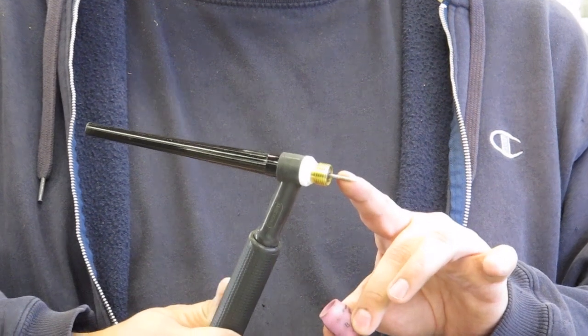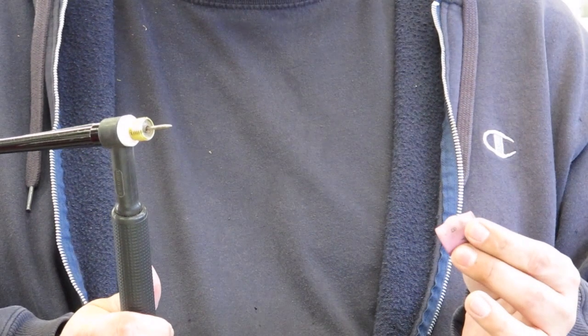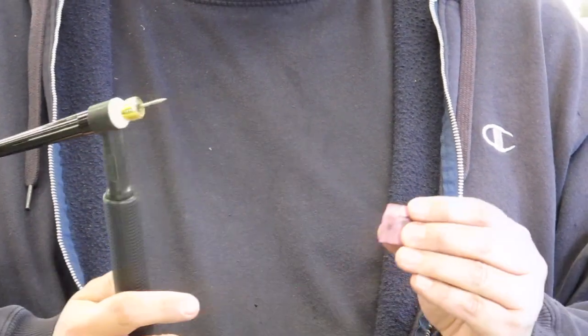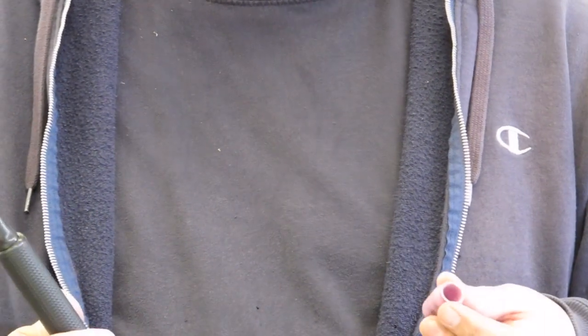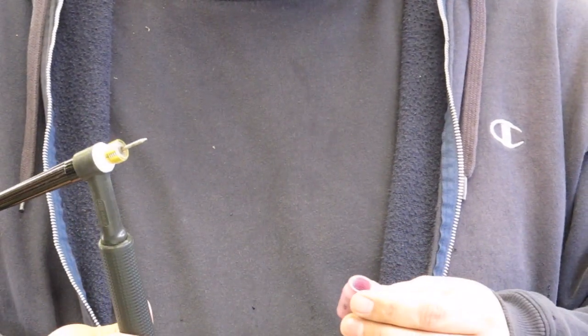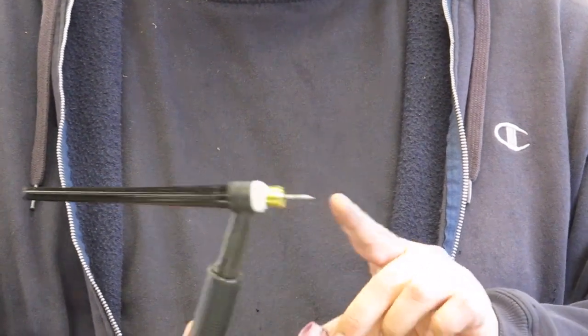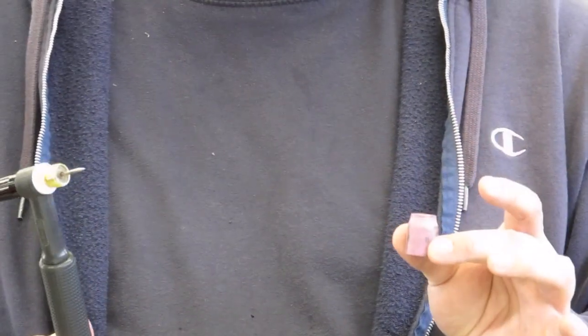That would be more than enough and not waste any gas. Now obviously I have an eight which is larger than I need to have. However, I like to have a larger opening on my alumina cup. I just feel I get better gas coverage with a bigger opening. I'm not worried about wasting gas, especially not on a paid project. I'd rather have the added gas coverage and the ability to stick the tungsten out further which is what you get when you have a bigger opening, particularly with a gas lens. So that's how that works.